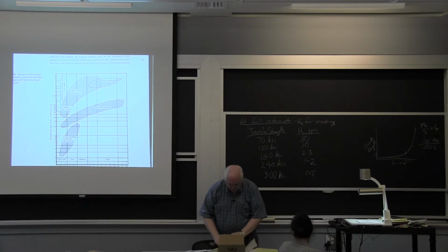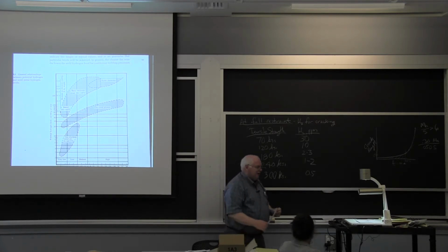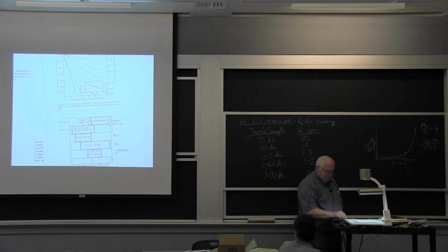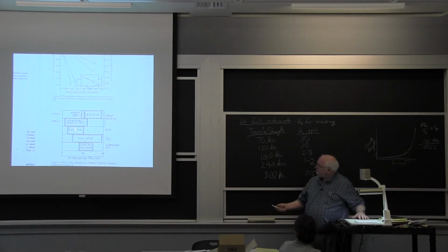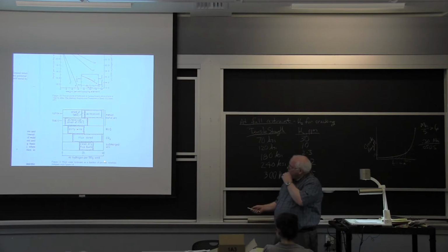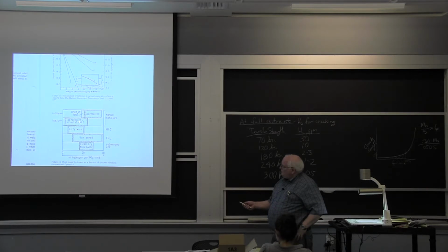Can anyone guess what my conclusion was? Pardon me? Well, we knew it was hydrogen cracking, okay? My conclusion was it was dirty wire. This is milliliters of hydrogen per 100 grams of weld, rutile electrodes, low hydrogen, basic, which is 7018, that's what they're trying to weld with. Dirty wire can give you regions of higher hydrogen than you would like to see in 180 KSI weld metal, clean, dry flux and wire, et cetera, okay?